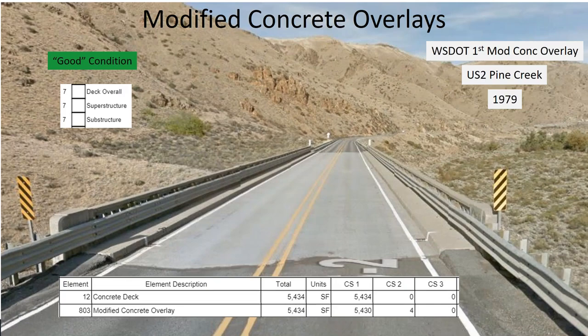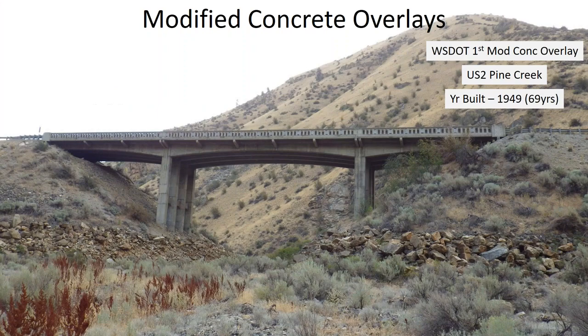Here's one of our earliest ones. It was put down in 1979. It's on Highway 2 coming out of Wenatchee. And you can see it's still in pretty good shape. So this might last the life of the bridge, since the bridge was built in 1949 and we're not seeing a lot of wear on this concrete overlay.